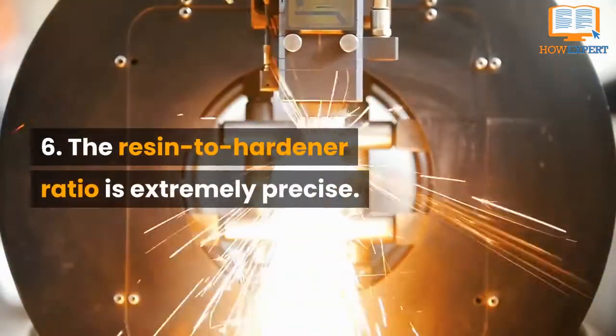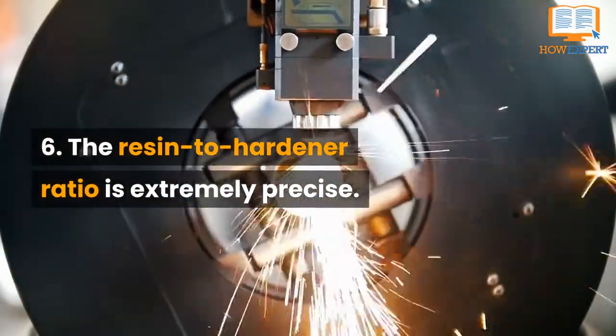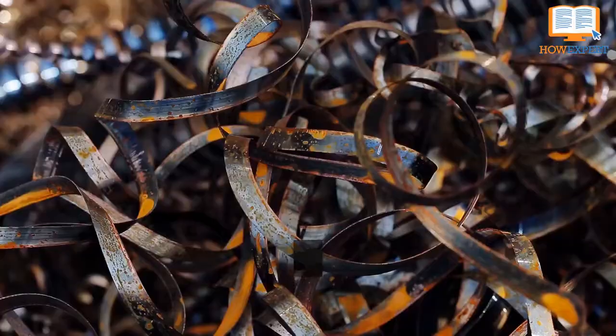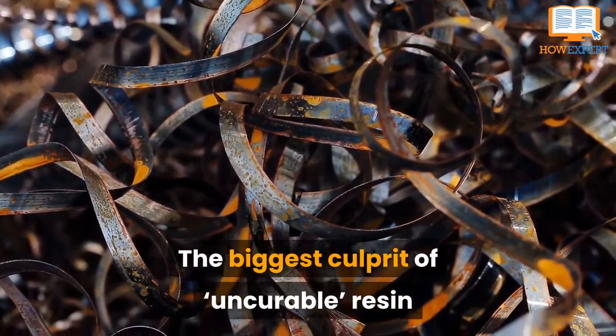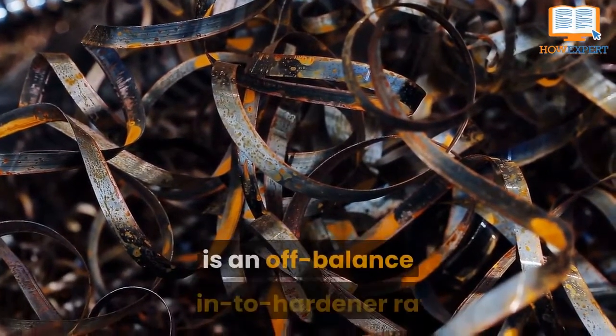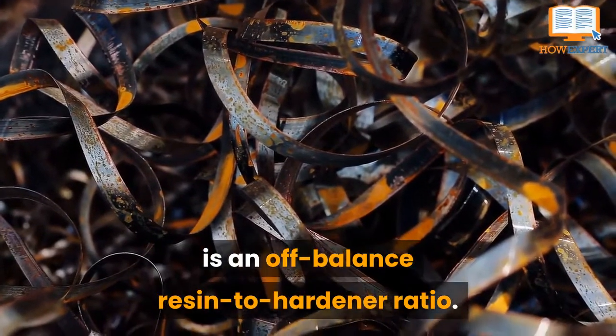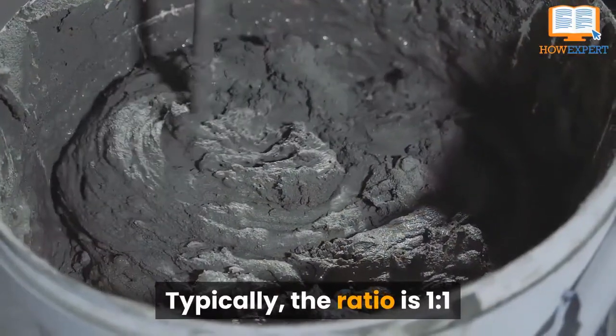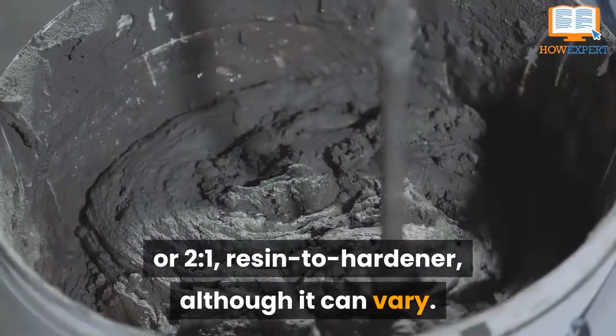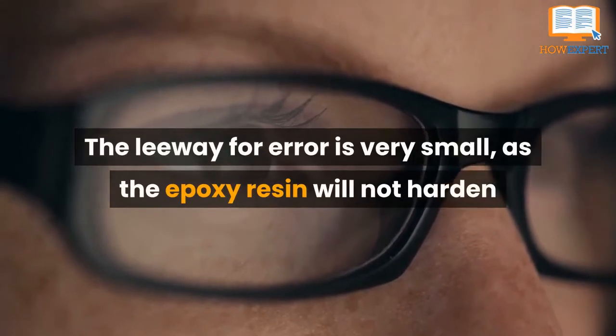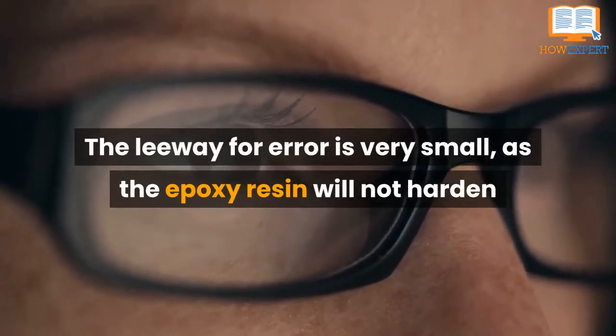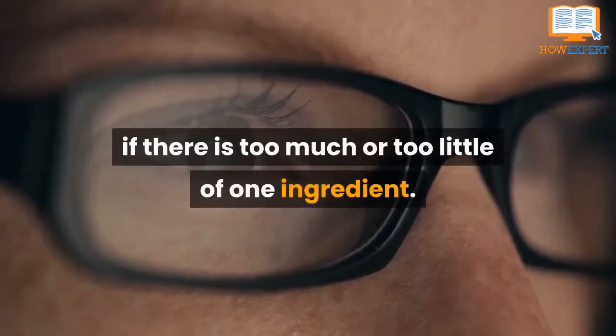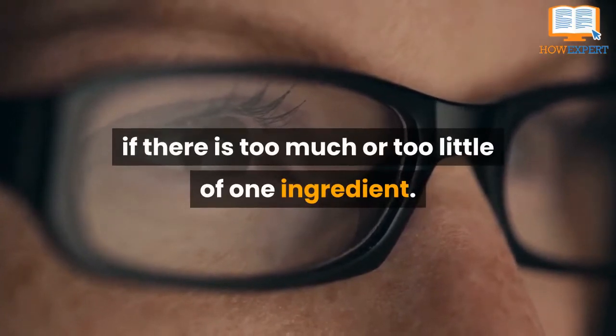Number 6. The resin to hardener ratio is extremely precise. The biggest culprit of uncurable resin is an off-balance resin to hardener ratio. Typically, the ratio is 1 to 1 or 2 to 1 resin to hardener, although it can vary. The leeway for error is very small, as the epoxy resin will not harden if there's too much or too little of any one ingredient.